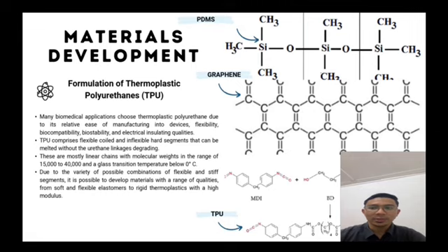So TPU comprises flexible coil and inflexible hard segments that can be melted without the urethane linkages degrading. These are mostly linear chains with molecular weights in the range of 15,000 to 40,000 and a glass transition temperature below 0 degrees C. Due to the variety of possible combinations of flexible and stiff segments, it is possible to develop materials with a range of qualities, from soft and flexible elastomers to rigid thermoplastic with a high modulus.